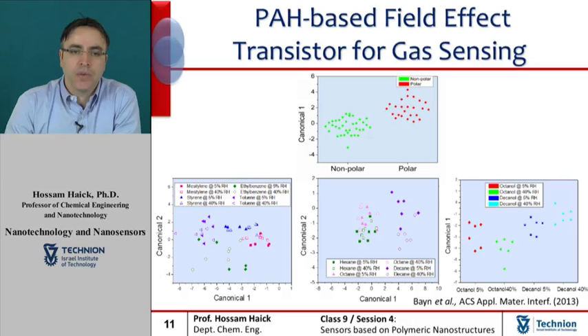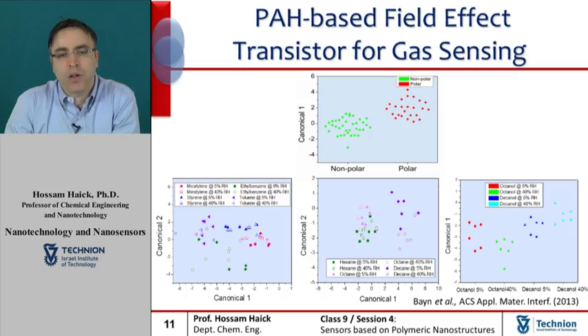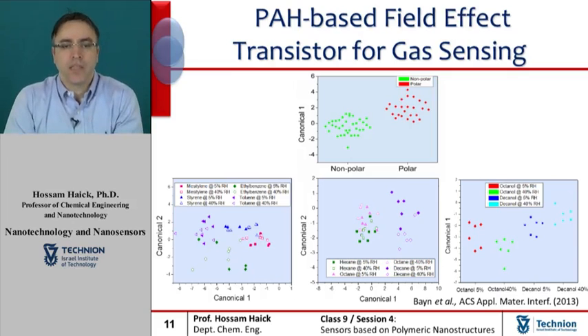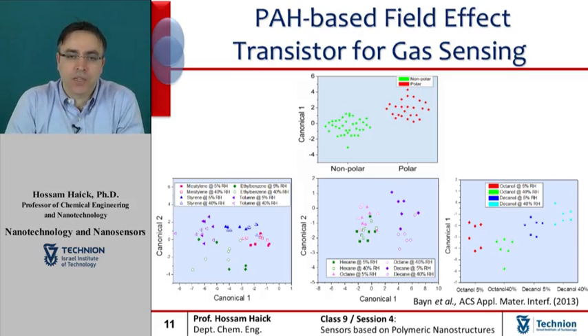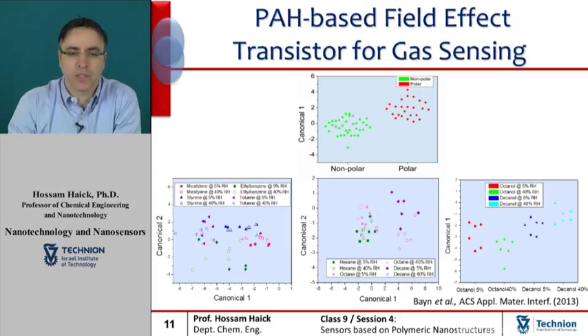In Figure C, you can see DFA results separating the non-polar volatile organic compounds, namely between hexane, octane, and decane, and the accuracy level of the discrimination between these groups was 75%. Now, we can see that Figure D shows DFA results separating the polar materials, namely between octanol and decanol, and the accuracy level of this discrimination between these two groups was 79%.